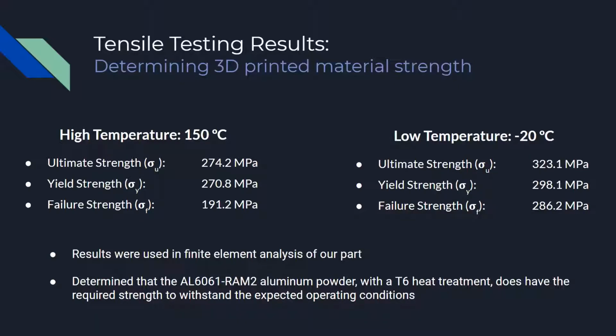We performed extensive tensile testing at 150 degrees Celsius and negative 20 degrees Celsius to simulate the potential environmental conditions these parts would be operating in. We did this in order to determine the ultimate strength, yield strength, and failure strength of the printed parts at these extreme temperatures. These results were then used in the finite element analysis of our part to determine if the parts themselves would withstand these extreme temperatures without failing. We were able to conclusively determine that the final iteration of our part will withstand the heat forces it will be exposed to over the wide range of environmental temperatures it's expected to operate in.